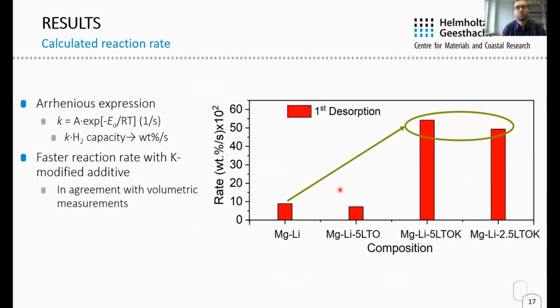As seen in this figure, the desorption rate of the samples with potassium is faster than the pristine sample. These contradictory results can be attributed to the increase in the frequency factor, which possibly leads to more efficient contact of the reactants at the interface.